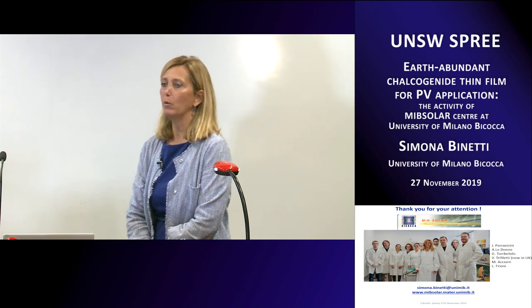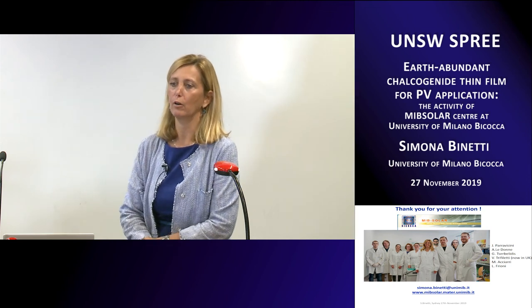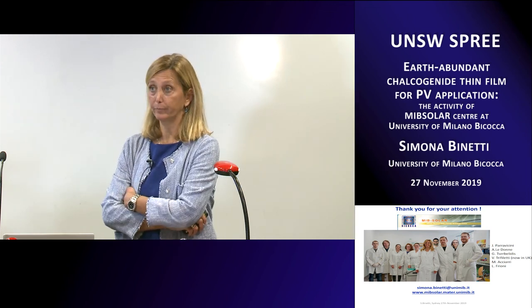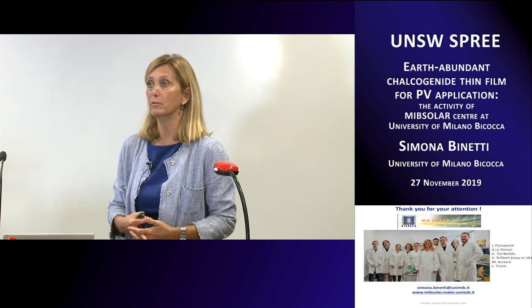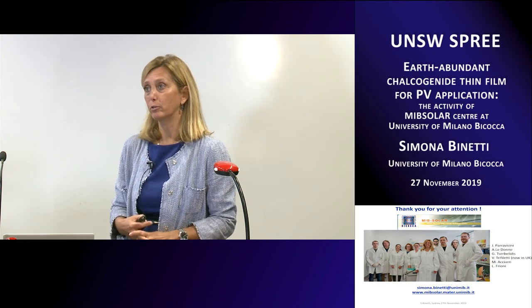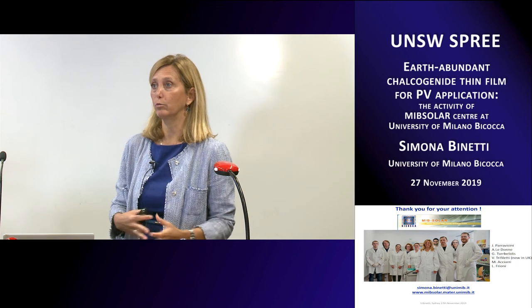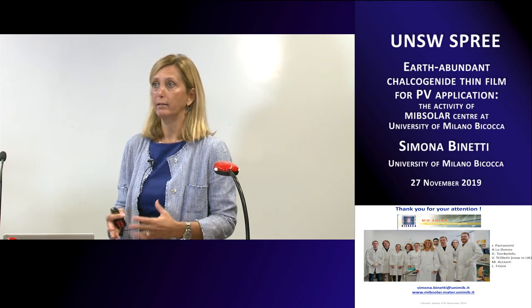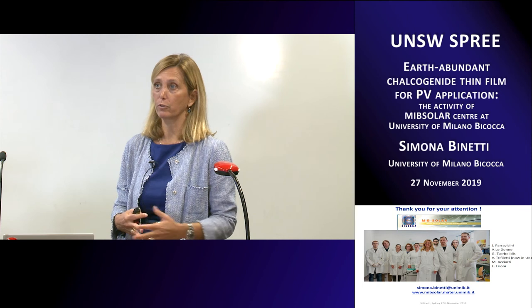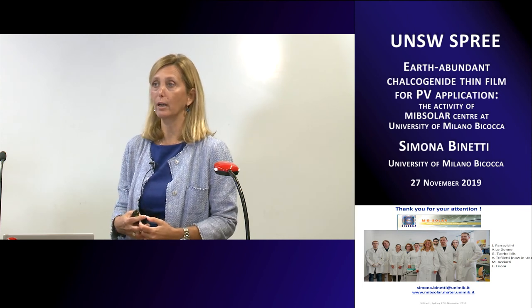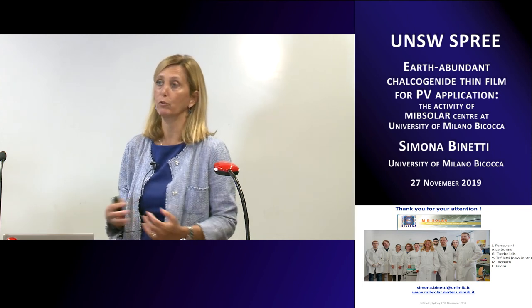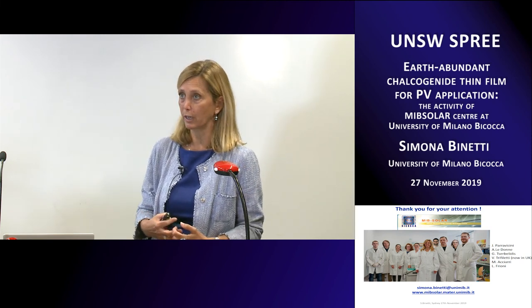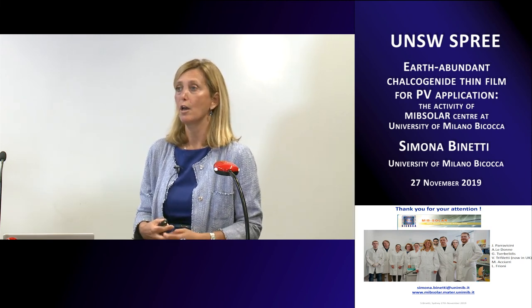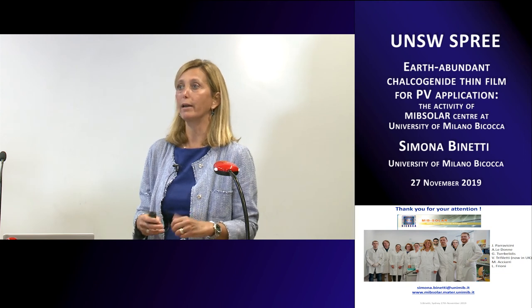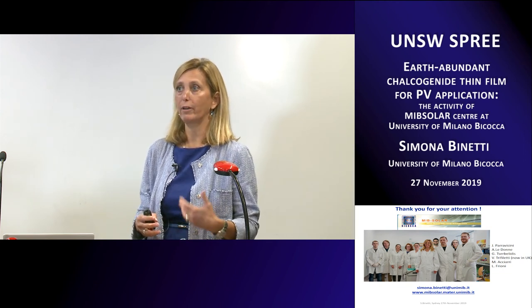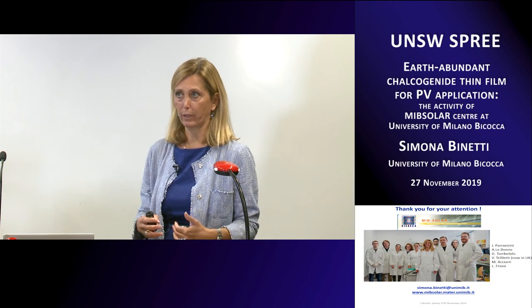Yes. The idea was to check the possibility of tuning the gap. So introducing iron, there are some very interesting literature articles related to the change of the gap, and there are some controversial ones, because according to some theoretical works there is an increase of the gap, and according to other works there is a decrease of the gap with the increasing of iron concentration. So the idea is to try to have a different material with a different band gap in comparison with Kesterite.